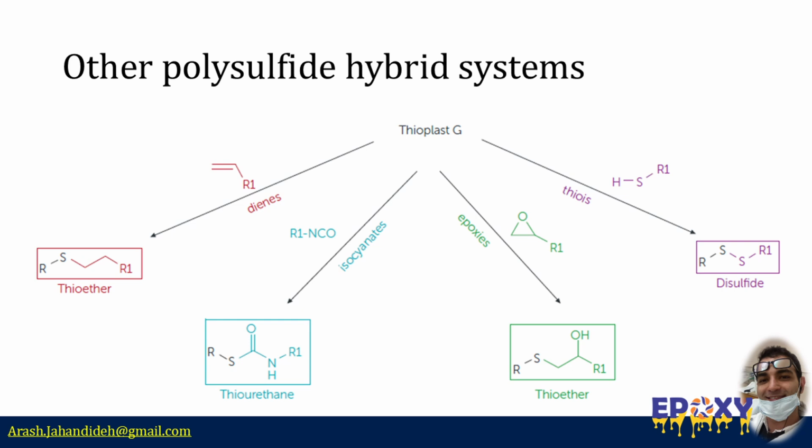One of the most commercially important reactions involves the stoichiometric addition of liquid polysulfides to Novolac or bisphenol A or F epoxy resins at ambient temperature. This process forms hybrid materials that combine the desirable traits of both components. The cure rate of these formulations can be significantly accelerated through the use of tertiary amines, such as